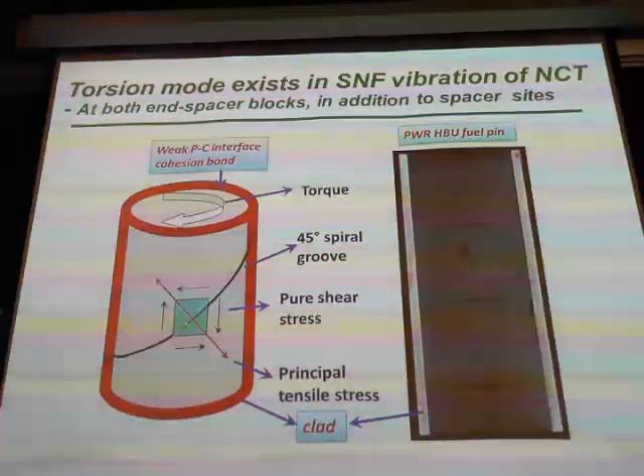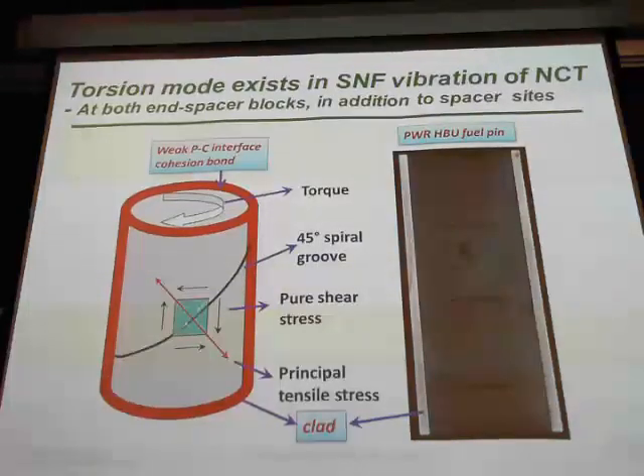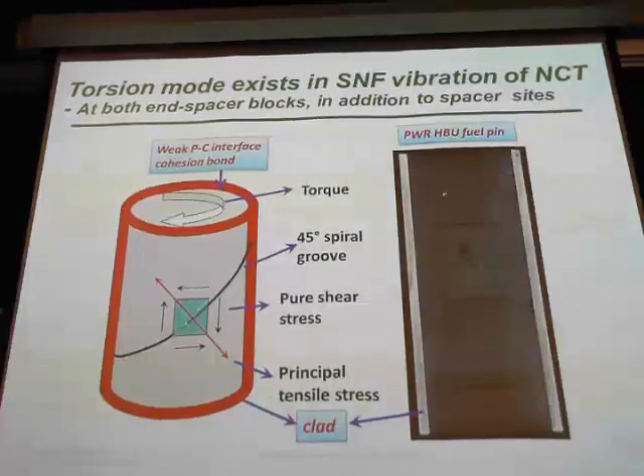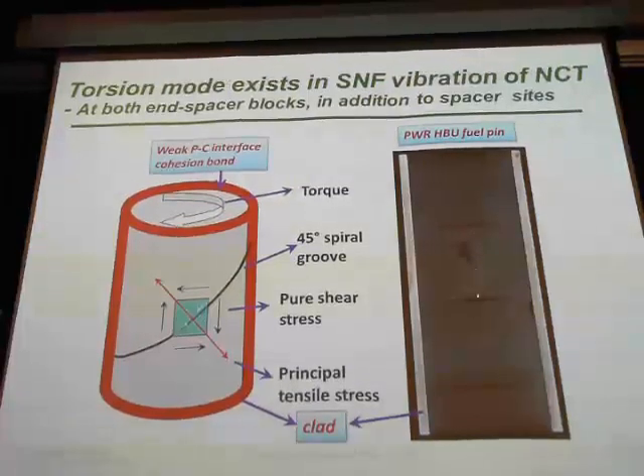I will talk about a little bit here. When we were little kids, we twisted a piece of chalk, what's happening? You generate a spiral surface when they break. This is called a principal tension test. Look at this, it's a spent fuel. This is real fuel from HB Robinson. The fuel pellet is very short, 0.237 inch. And we found that pellet length does matter. Longer pellet length gives higher stiffness, and shorter pellet length bends more easily, but they survive more. So this is really interesting.